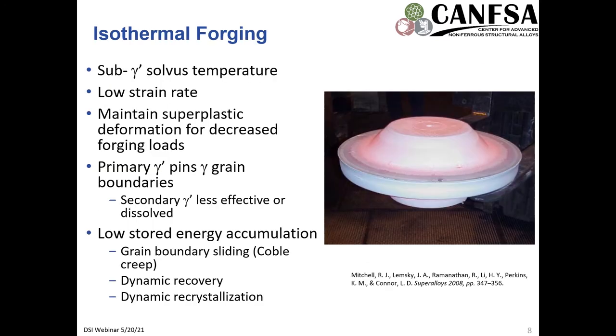So to go into a little bit more detail about isothermal forging, this is done at sub gamma prime solvus temperature, and this is done at a low strain rate to try to maintain superplastic deformation for decreased forging loads. And nominally, we're trying to have a minimal amount of microstructural evolution occurring during this, but there is still some. And at this temperature, the primary gamma prime serves to pin the gamma grains to maintain a small gamma grain size and have superplastic deformation. And that's how it continues at high temperatures. And nominally, we have a low stored energy accumulation, and this is achieved through having grain boundary sliding or Coble creep occurring, as well as some levels of dynamic recovery and dynamic recrystallization.